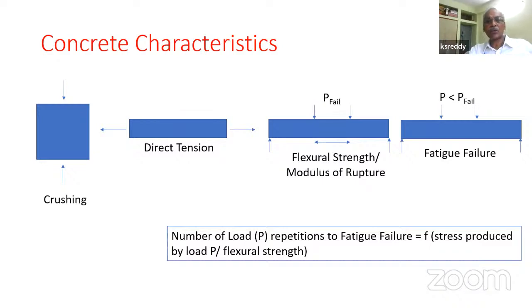Now, when you characterize the concrete material for various purposes, when you're trying to explain different kinds of pavements, there could be crushing, small blocks. There is no contraction cracking because it is too small a slab to be worried about contraction cracking, because there is hardly any restraint, and the slab is too small. Right. But they could be subjected to crushing. So crushing is an issue. Direct tension, when you got large panels and you cut a groove there, whether it's going to crack or not, is because when it is trying to contract. So this would be a case which is more relevant for direct tension instead of flexure or crushing.